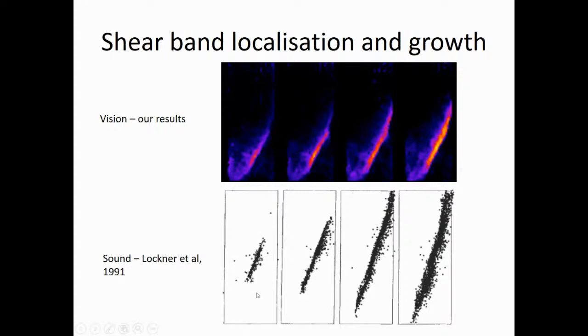We could actually reproduce what the acoustic emissions were showing, and that gives you an idea that it is a sensible thing to make inferences from acoustic emissions, and that they are capturing pretty much the most important things in this example. This is not like for like. We haven't got this number of locations because we're using such a small sample, but it shows a nice correlation.